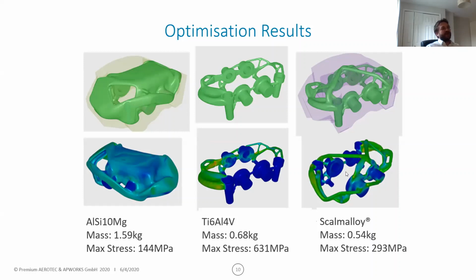What was interesting and actually not entirely expected, to be honest, when we started the study, was that Scalmalloy would be lighter than Ti 6.4. We expected, based on specific properties, that the Ti 6.4 solution might be a bit lighter, or that they would be similar. And what we concluded was that this was mainly driven by the non-design space. So all these features, in this case, these cylinders for the pistons, which are mandatory. So let's say anything where you just can't topology optimize it, you need that feature. Of course, with a lower density material, if you're limited by a particular feature geometry, you might call it parasitic mass or whatever you want to call it, there's less mass in those features. So that is also a factor to consider. If you have a part where it can completely be optimized and there's no parasitic mass, then titanium might give you a lighter solution.